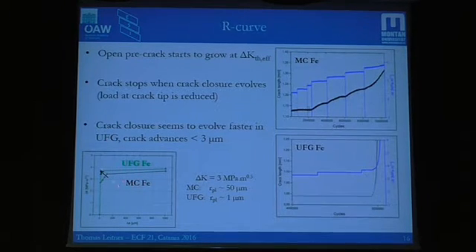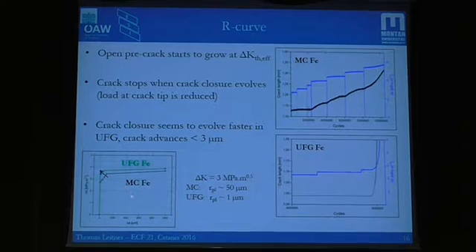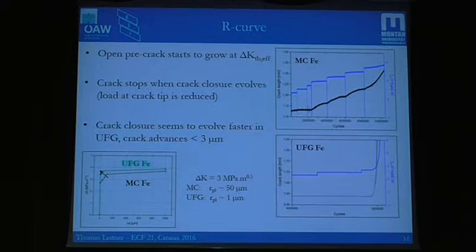So what we get in the end is just a very steep cyclic R-curve. Why is that the case? Well, the crack closure evolves when a crack propagates through the plastic zone. The sizes of the plastic zone are quite different: for the microcrystalline microstructure we have a cyclic plastic zone size of about 50 micron, and for the ultrafine grained iron we have a plastic zone size of about 1 micron. So already from these figures, it would be expected that the crack extension in this R-curve regime is quite small, so we can't detect it anymore.